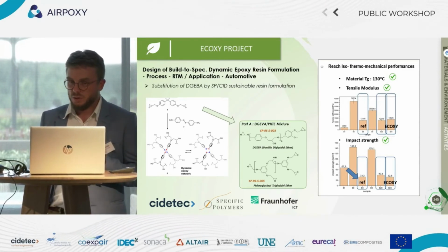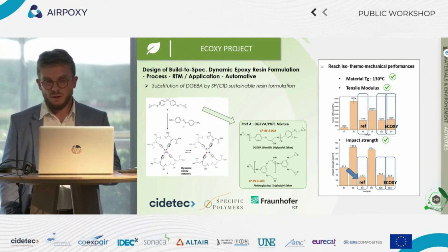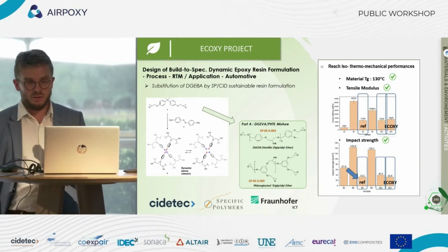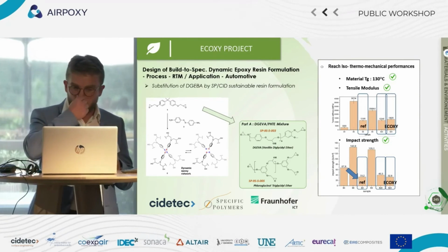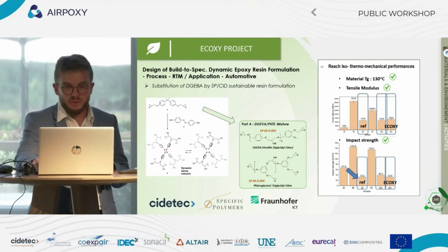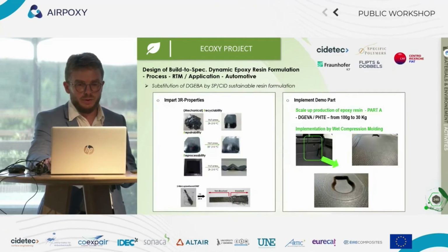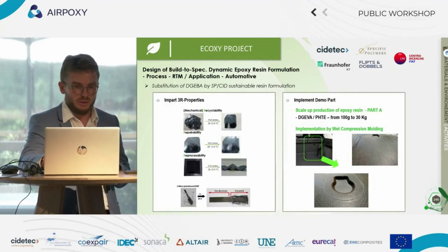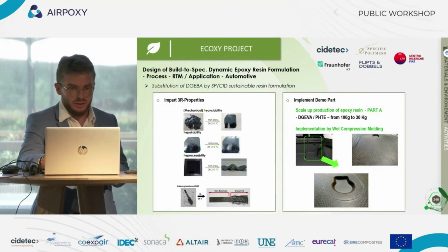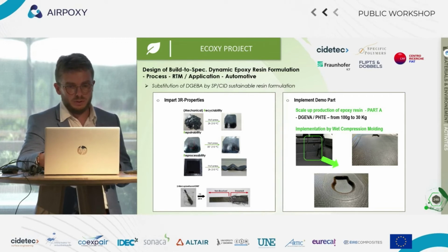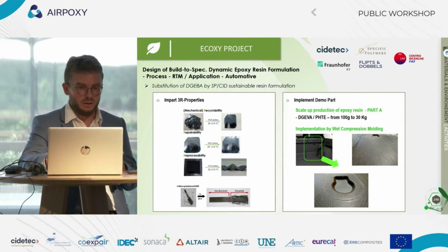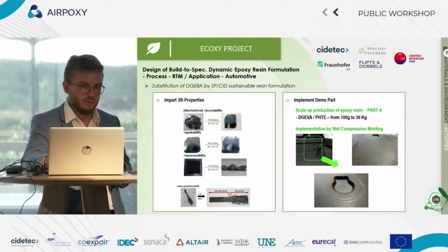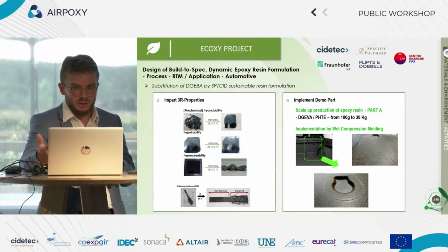In terms of TG, it was 130, the objective here, in terms of tensile modulus, and also in terms of impact strength. So this was really interesting. We figured out the best formulation to push further, and then we worked with the partners, and especially Cidetec, to evaluate the 3R properties. The results are here, and it shows whole aspect of the recyclability that are in the 3R.